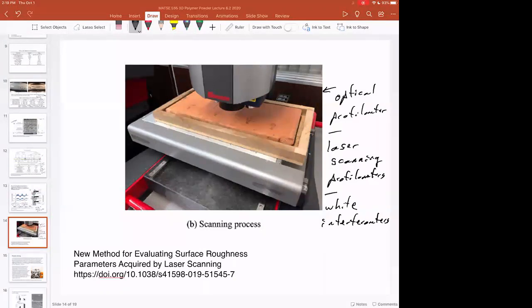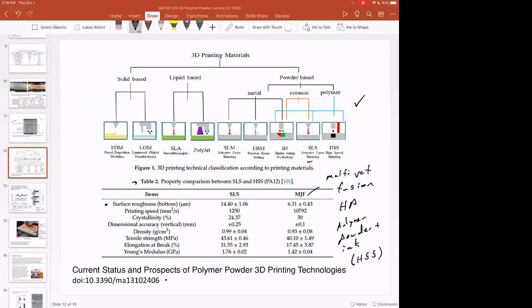So an RMS roughness of 1 micron is pretty smooth. And RMS roughness of a silicon wafer that's basically a mirror finish is on the order of a couple nanometers, whereas the RMS roughness of something like an SLS surface will be 50 microns or 100 microns or something like that. So you can see the dullness of the surface finish just from the scattering, or the RMS roughness of, say, a piece of printer paper is on the order of 20 microns or something like that. And so the RMS surface roughness gives you an idea of the surface quality. And of course, different printing techniques, whether it's powder-based or whether it's liquid-based or something else, will have different surface roughnesses. And so that will matter as you start to think about what process you're going to use, coupled to what material you're interested in and what application your product's going to be used in.